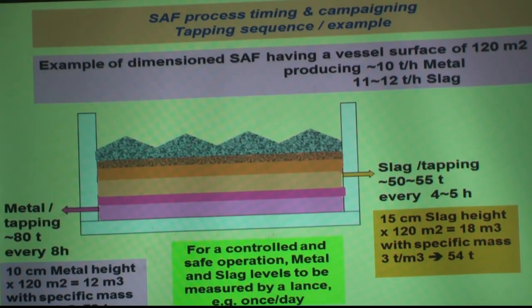In practice, of course, you have the ladle, or you have the troughs that you fill. You see when they are full, and then you stop. But just to calculate the amount, in a large shaft, if you tap something like 80 or 100 tons, it is a small height. It's not much. But that is good for the stability of the process. Because if you had everything descending by half a meter, this is not good. Then you disturb everything. Half a meter is huge. But 10 centimeter is a good height.